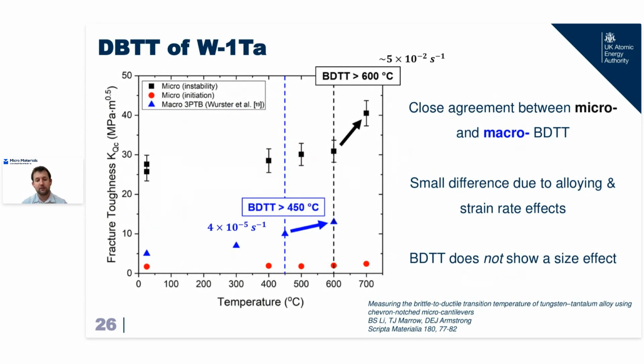One of the really nice things that Bo showed is that the micro and the macro BDT are very, very close to each other. There is a small difference in the raw number between the micro data and the macro data, but that can be attributed to the higher strain rates in the small scale testing, as well as the fact that we're looking at a tungsten tantalum alloy rather than pure tungsten. But essentially, we can conclude from this that the brittle ductile transition temperature does not show a size effect, which is an absolute wonder for small scale testing, where everything else really does.